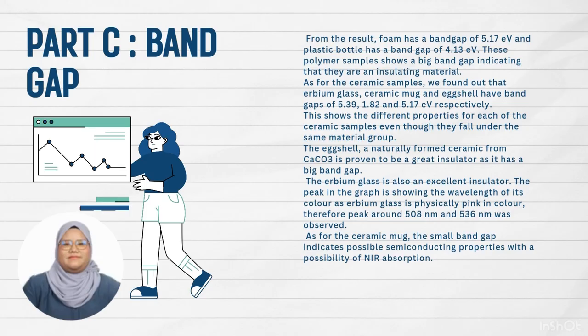Lastly, part C, the band gap. From the result, foam has a band gap of 5.17 eV and plastic bottle has band gap of 4.13 eV. For both of these polymer samples, they show a big band gap, indicating that they have an insulating property. As for the ceramic samples, we found out that erbium glass, ceramic mug, and eggshell have band gaps of 5.39, 1.82, and 5.17 eV respectively. This shows the different properties for each of the ceramic samples, even though they fall under the same material group. The eggshell, naturally formed ceramic from CaCO3, is proven to be a great insulator as it has a big band gap. The erbium glass is also an excellent insulator.